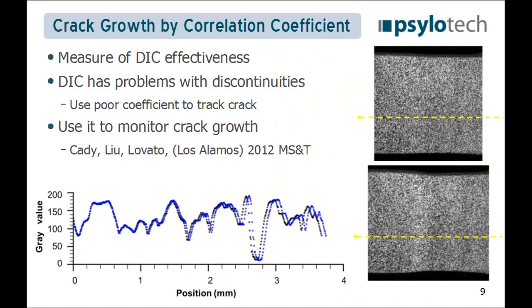Another interesting technique that I've seen in the last few years, oh, I went up 2 slides, sorry about that. Digital image correlation has a problem when new features come up. The way that it basically works, in a very rudimentary way, is you pick a pixel, and then the software takes a curve fit of the pixels around it to know how much that one pixel moves from image to image. So in this case, you can see there's a line of pixels, and this is the grayscale level, and that's how it knows that it moves and how it can track it to below pixel resolution. The problem happens when there's a crack and you end up breaking this. It's difficult for digital image correlation to find how much motion happened because there's a new feature that's different from one image to the next.